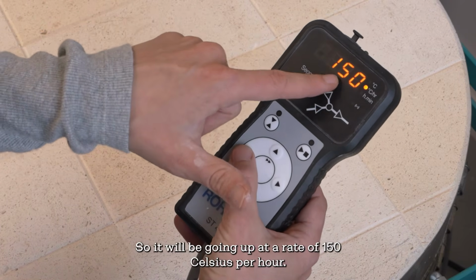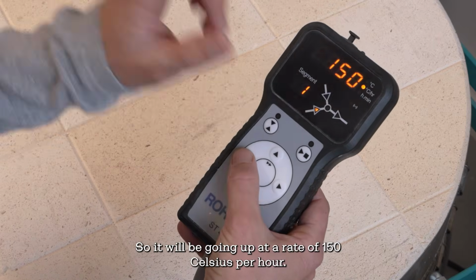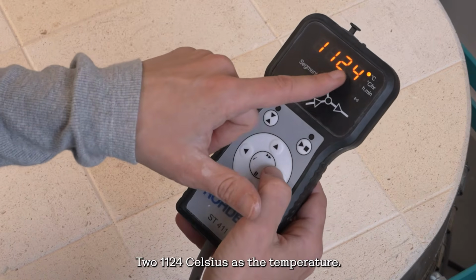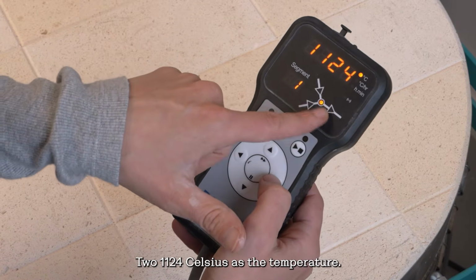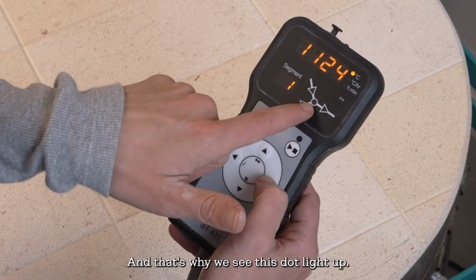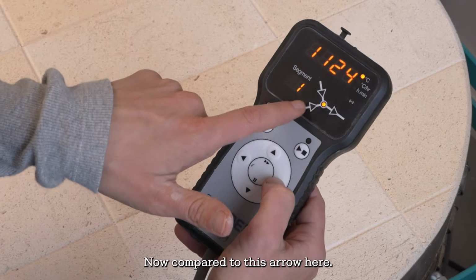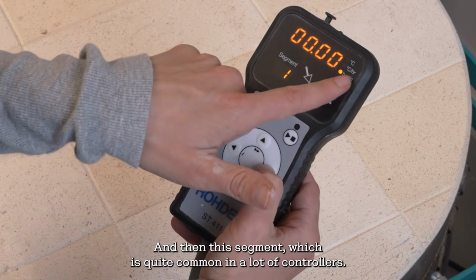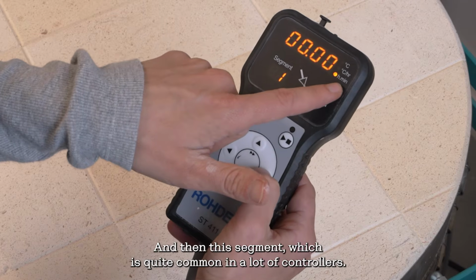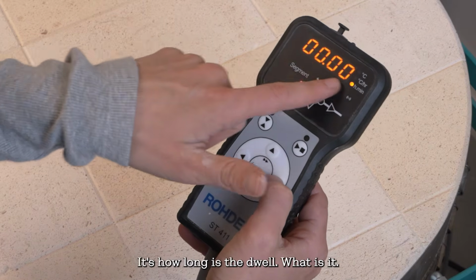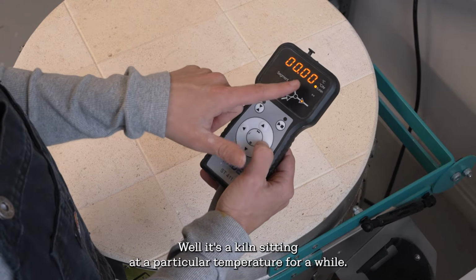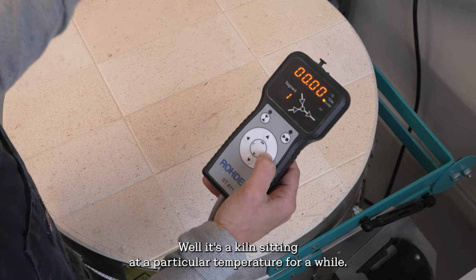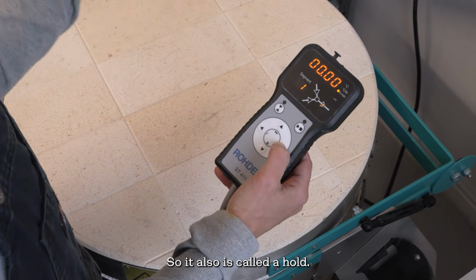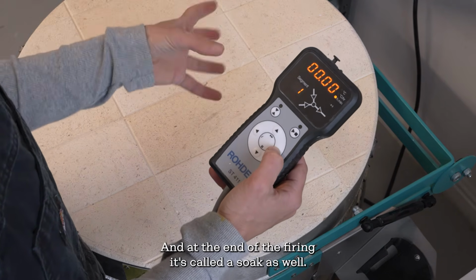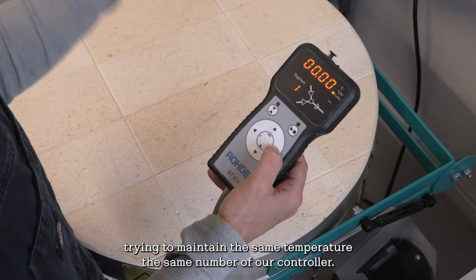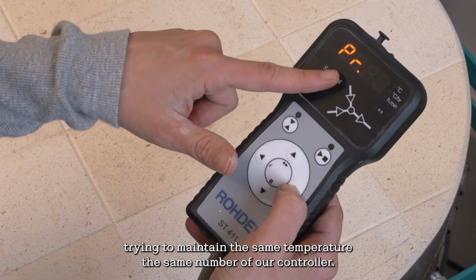that it's reaching. So it will be going at a rate of 150 Celsius per hour to 1124 Celsius as the temperature, yeah? And that's why we see this dot light up now compared to this arrow here. And then this segment, which is quite common in a lot of controllers, is how long the dwell is. What is a dwell? It's a kiln sitting at a particular temperature for a while. It's also called a hold, and at the end of the firing it's called a soak as well. So it's basically trying to maintain the same temperature, the same number on our controller.